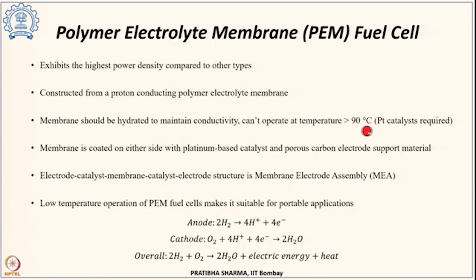The electrocatalysts used are platinum, and these are coated on either side with platinum based catalyst and a porous carbon electrode support material. The combination of electrode, catalyst, then membrane and the other side catalyst electrode structure, this combined structure is known as membrane electrode assembly. Since they operate at less than 90 degrees centigrade, because of this low temperature operation, polymer electrolyte membrane fuel cells can be used for various portable applications.